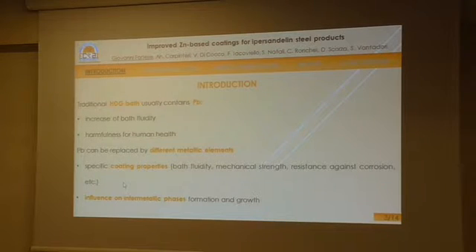Traditional hot dip galvanizing baths usually contain lead that increases the fluidity of the bath, but at the same time can be very harmful for human health. Therefore, lead can be replaced by different metallic elements in order both to obtain the requested bath fluidity and to give different and specific properties to the coatings, for example, an increase in mechanical strength or the resistance against corrosion, influencing the intermetallic phases formation and growth, which can be different from those of a traditional zinc-based coating.